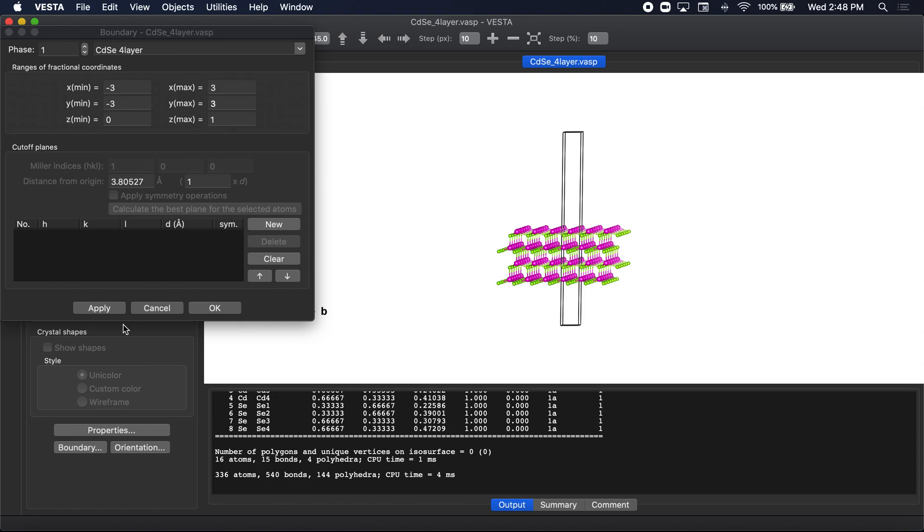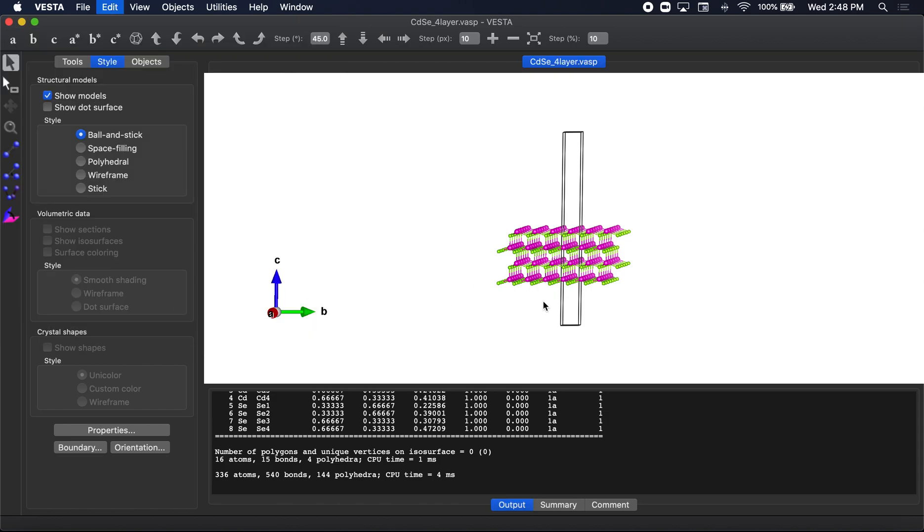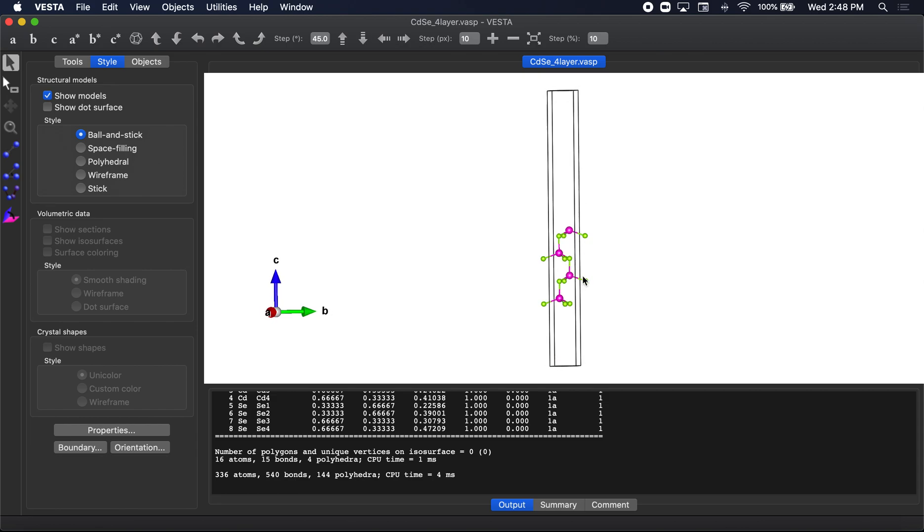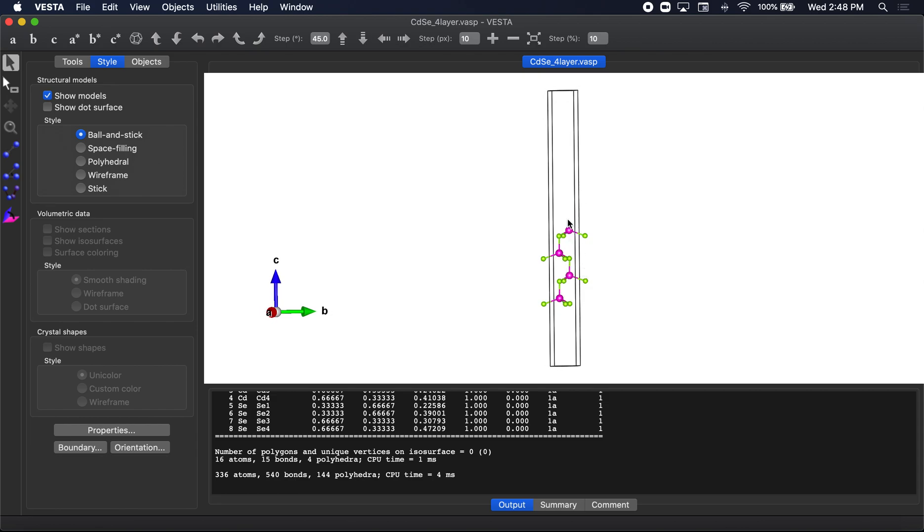Well the easiest way to do that would be to keep the structure small, just have it be simply just this kind of one unit cell thick in the a and b dimensions, and just manually place a hydrogen roughly 1.7 angstroms above the cadmium. That turns out to be the cadmium hydrogen bond distance.